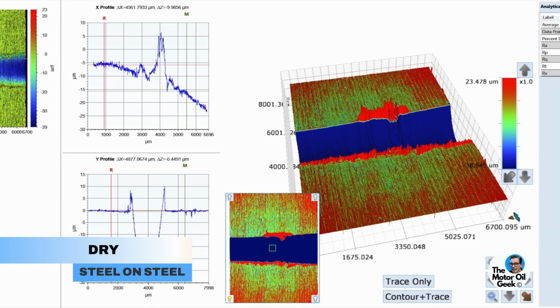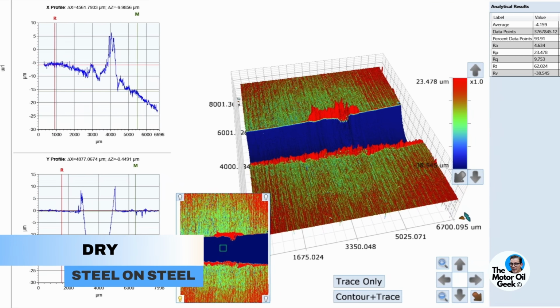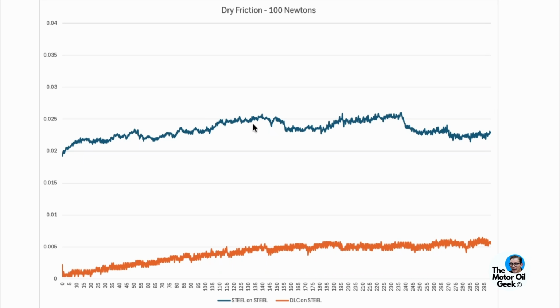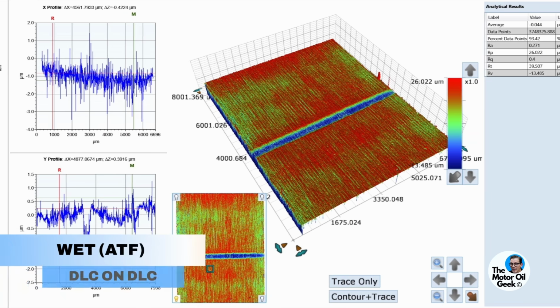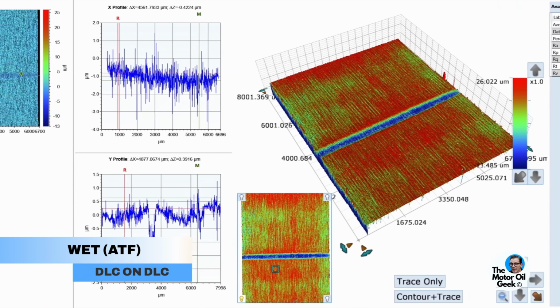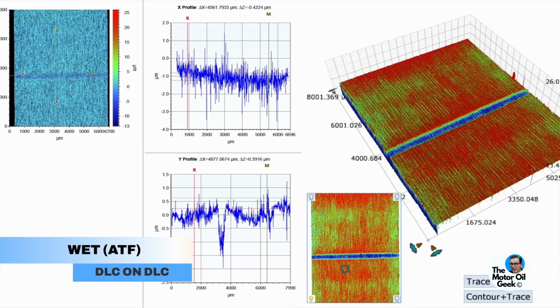off with time. The channel might be called the Motor Oil Geek, man, but Peter, I love tribology more than I love motor oil, and these results probably show that. Oh, they do. So when you look at the wear for the steel on steel, that was really high friction. That's what we expected. Right, it's steel on steel, like you should not do that. High friction, high wear. And then we do DLC on DLC, really low friction and really low wear. Added some oil in. And it hardly changed the friction or the wear. It was pretty crazy.